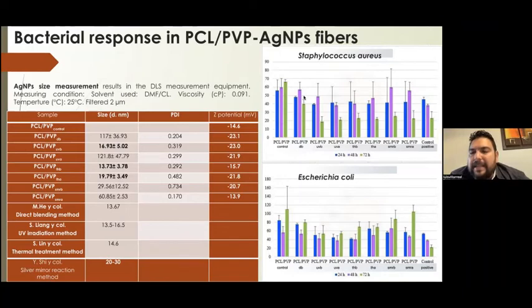And as you can see in this antibacterial testing, using a microdilution test with Staphylococcus aureus and E. coli, you can see how the presence of the loaded fibers after 24, 48 and 72 hours creates much alteration in the cellular replication of these bacteria, reducing growth by more than 50% in Staphylococcus aureus, and 60% in E. coli. So that's our desired result for this application of wound dressings.